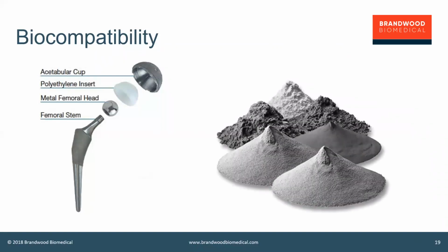But the starting materials for additive manufacturing look like this. This is just a picture of some of the metal powders that might be used in additive manufacturing, or you might be using polymers in a polymeric device, reels of polymer that feed into a 3D printer. The question then is not so much what's the composition of those little piles of powder, but what's the composition of what comes out at the end. And you can source titanium powder, which is claimed by the manufacturers that once it's been put through a defined additive manufacturing process, complies with the ASTM standard for titanium surgical alloy.